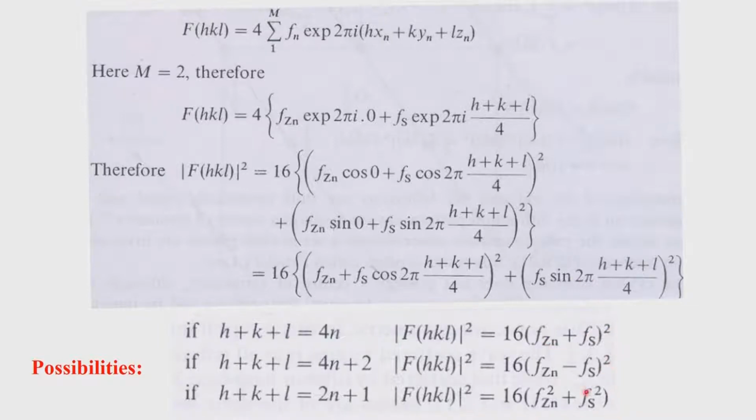Only those reflections will come because zinc and sulfur are sitting in special positions in the F lattice. So, the F lattice anyway exists, and over and above that you will have additional conditions, which seem like absences but are not really absences, over and above the conditions that are present in the F lattice.